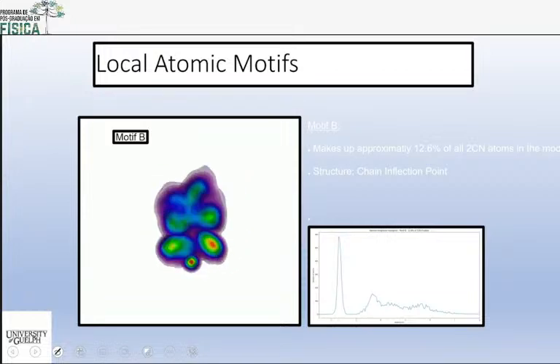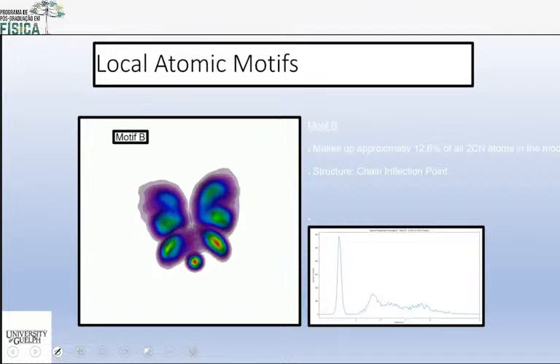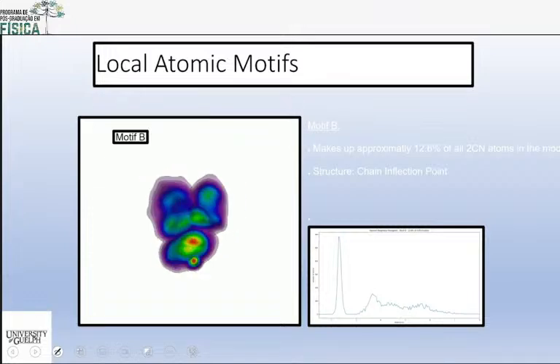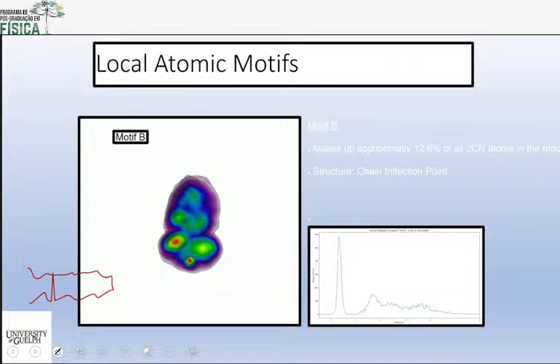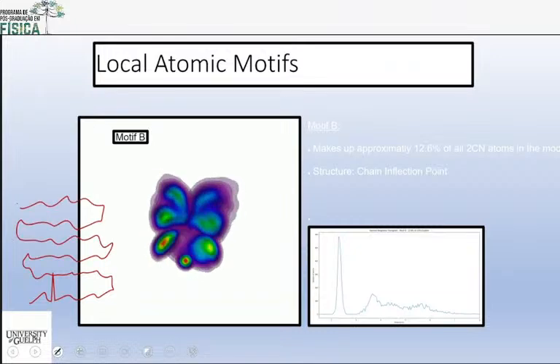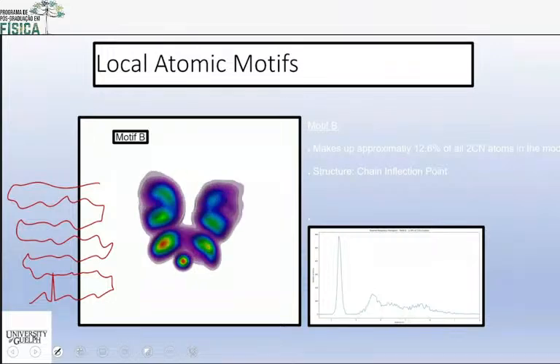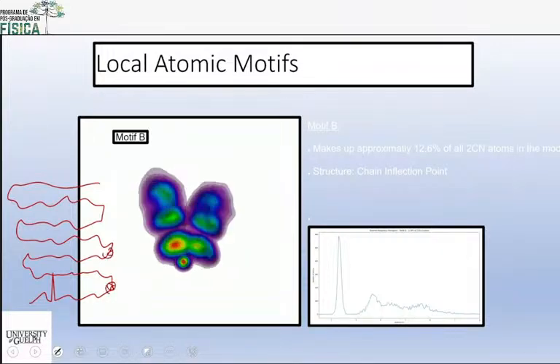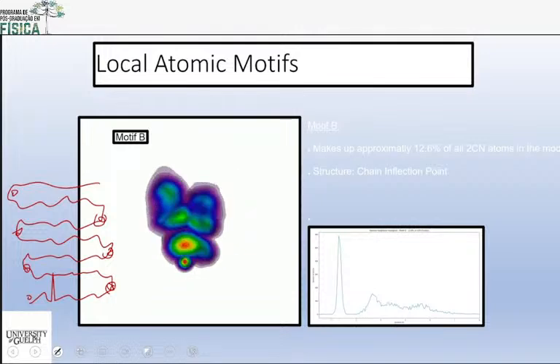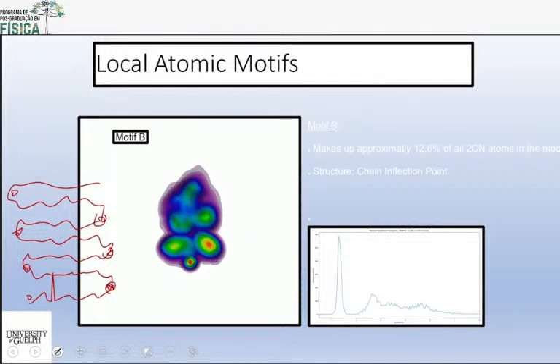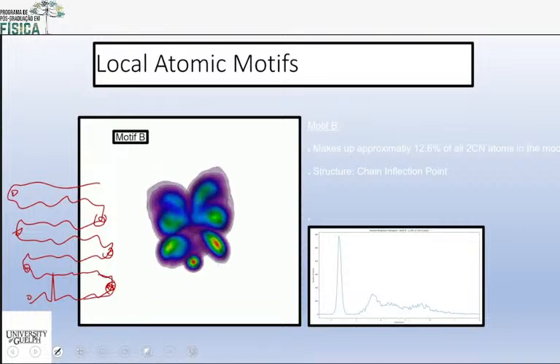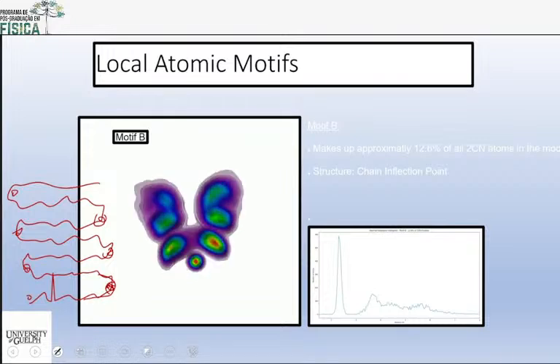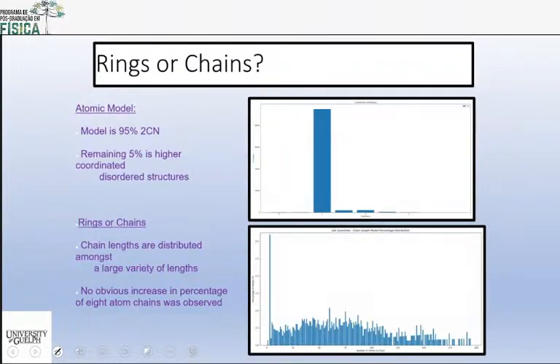12% had this arrangement. And you say, oh, is that the 8-atom ring? 1, 2, 3, 4, 5, 6, 7. No, it's not 8, and it's not closed. See, what I think is happening is that selenium actually does this. And 12% of the atoms in the selenium are exactly where the chain folds back on itself. Isn't that cool? So even though the pattern isn't a crystal, we can say something about it. And we don't have any 8-atom chains in the model either.